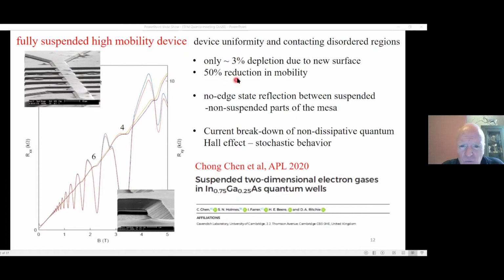We get a reduction in the mobility, but in the thicker layers we only get a very small depletion of charge. We've created a new surface, and there are surface states associated with that. But in these slightly thicker layers, we just don't see that. We also are very lucky that with the processing that we use, there's no edge. You can go into the edge state transport regime, the quantum transport regime, and there's no edge state reflection in the system. You can properly measure the 2D parts of the system. And we did a quick study on this a few years ago, looking at the breakdown in non-dissipative behavior to really try and understand what these thermally isolated systems look like.